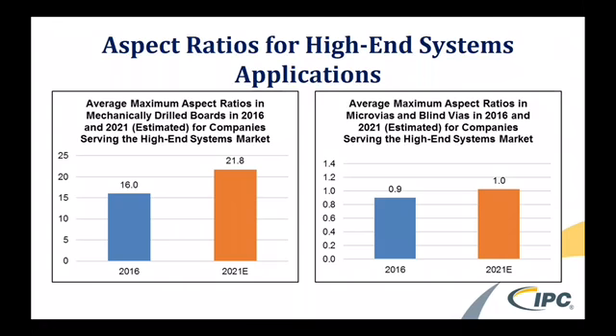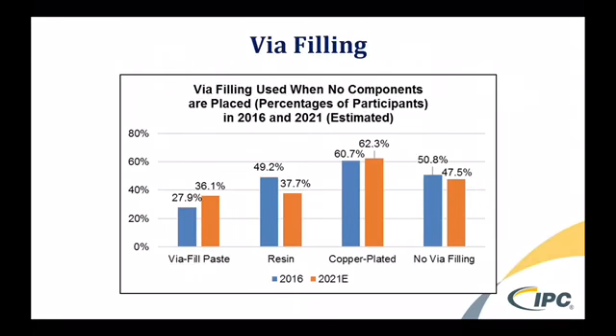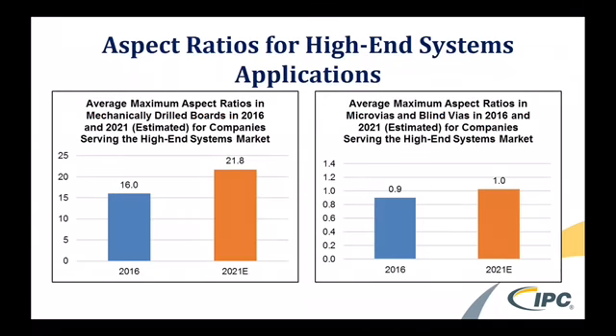So we picked this particular group to highlight here because of the significant high aspect ratio that we're seeing in terms of the plated through holes. As you can see already, that number is a 16:1 aspect ratio in 2016 for these high-end applications, moving to almost 22:1 by 2021. And on the right side of that slide, you can also see where they expect the aspect ratios for micro vias to be.